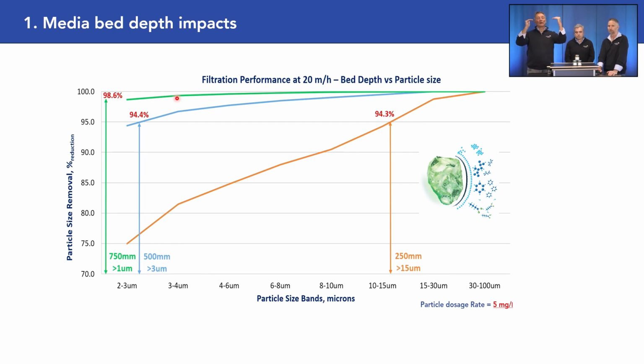We have tested the filtration performance of different bed heights. Green is a 750 millimeter bed height, where we got 1 micron filtration at 98% removal efficiency. So even better than the 95, but usually at 95, at 500 millimeter filter bed, we got to 3 micron. And then with 250, you see we are at 15 micron. So it's a big gap.